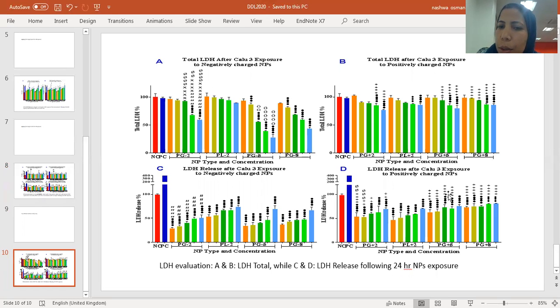So it was an easy way to spot the interference that can happen with the nanoparticle in the release assay. Now, you will see some of the literature presenting the nanoparticle LDH release assay as not causing any issue, while this could literally be an effect of nanoparticle absorption of this cellular protein, giving a false negative response.